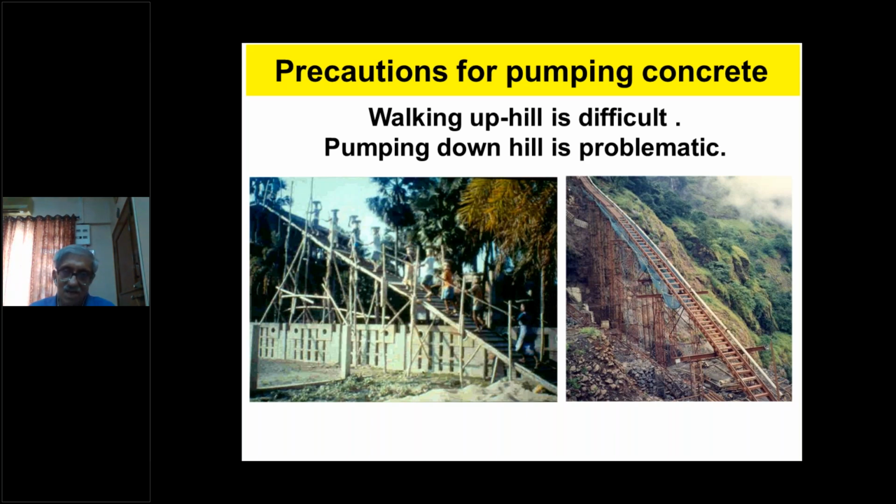The problem is that many a time the concrete just slides down and creates air pockets, and many a time, as you see even in water lines, we get airlocks. So we started getting airlocks, and the concrete pump would not pump. Ultimately, we decided that we will pump from the downstream and upwards into the anchor blocks. And that worked beautifully because our pumps were quite powerful and we could get the mix to go very easily.